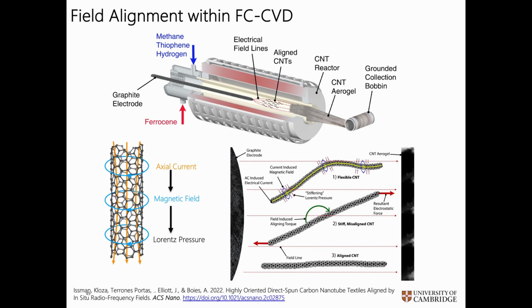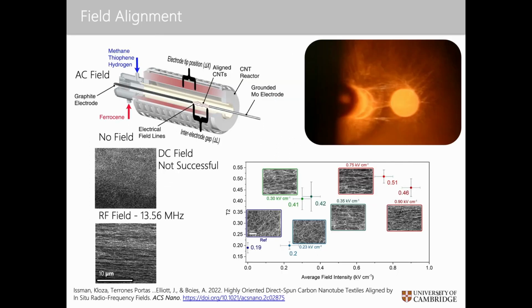And so if you have electrons moving back and forth in an alternating field, you get, by Maxwell's equations, a magnetic field that goes around that, and that serves to stiffen the nanotube. And once it's stiff, you can imagine you can align dried spaghetti. You can't align wet spaghetti, right? And so you need to dry the spaghetti, so to speak, first to be able to then align it in a useful way. And when you do that, it works really well.